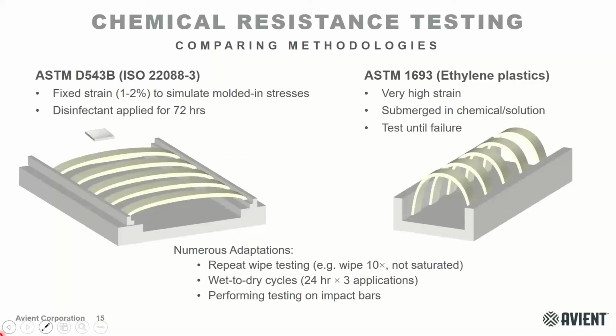So I want to talk a little bit about how do we test for chemical resistance in the lab. And I'll start with the one on the right. ASTM 1693 is a test for ethylene plastics. This was originally created because they noticed that cross-linked polyethylene tubing and wire and cable were showing failures in the field because they were frequently being treated with surfactants or soaps to help feed the tubes and the wires. And so this is really kind of specific to ethylene plastics.